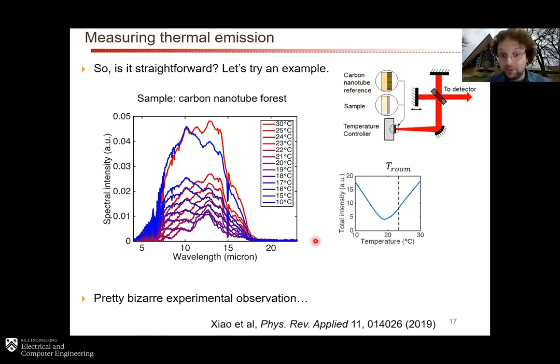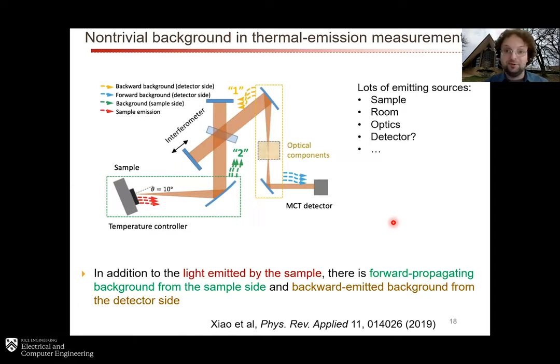If you integrate over all wavelengths and you get the total intensity and you plot it as a function of temperature, you see that there's this minimum over here, and the minimum in our experiment at least is just a few degrees below room temperature. And we actually went to our physical plant, to the folks that maintain our lab, and we asked them to change the temperature of our lab room, which turned out to be more difficult than one would expect. And we observed that this minimum followed the temperature of the room. So it was always some number of degrees lower than the temperature of the room. And so clearly this is some sort of an artifact.